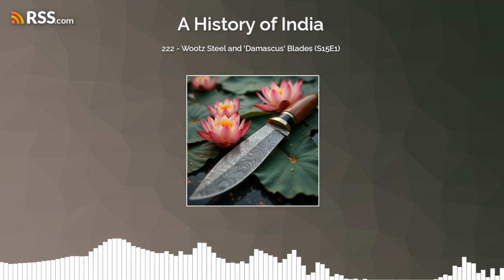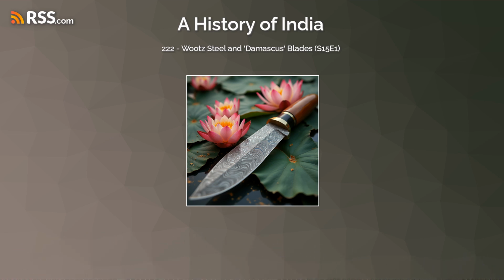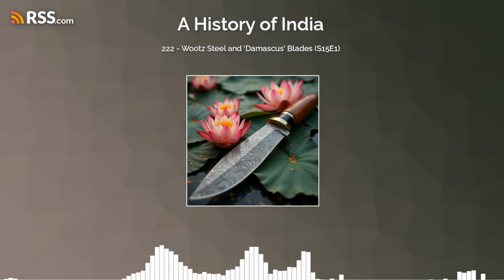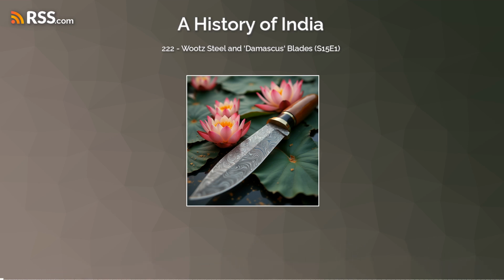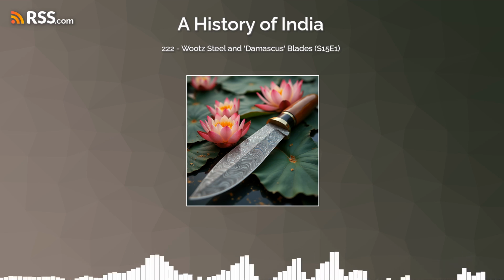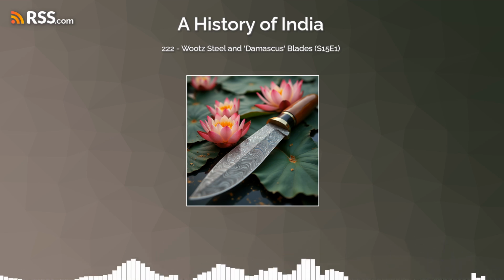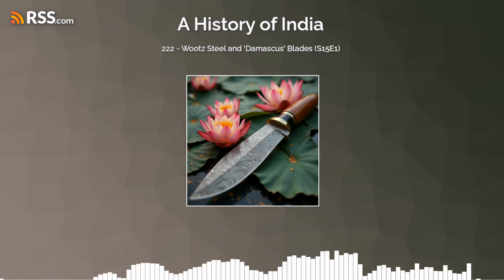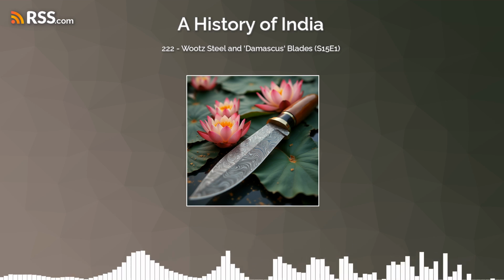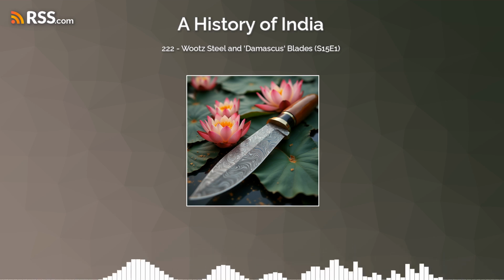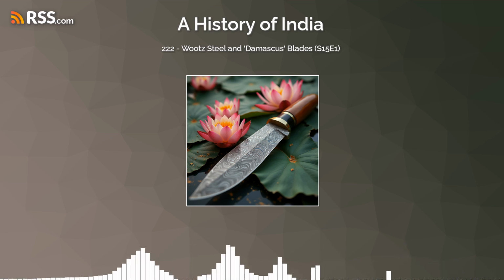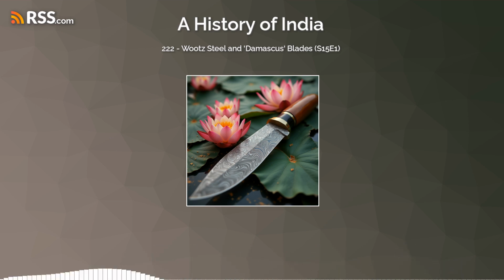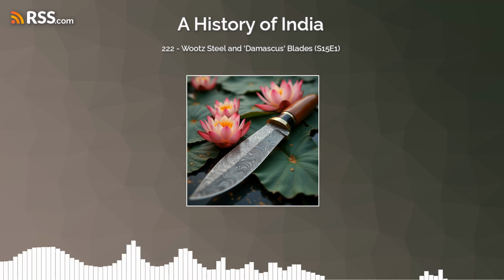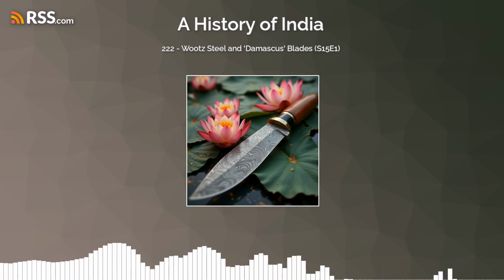Ah, so forging and etching were needed to reveal it. Precisely. The etching process attacks the different microscopic phases in the steel, the softer, iron-rich ferrite and the harder, carbon-rich cementite at different rates. This differential etching is what brings out the underlying structure, which the forging process had already aligned and refined into those characteristic bands or swirls. Let's get more into the science of that pattern and the steel's amazing properties. You mentioned cementite and ferrite.